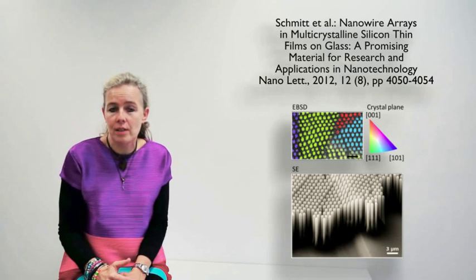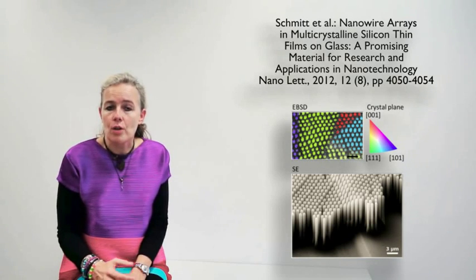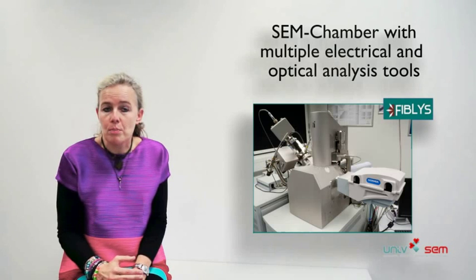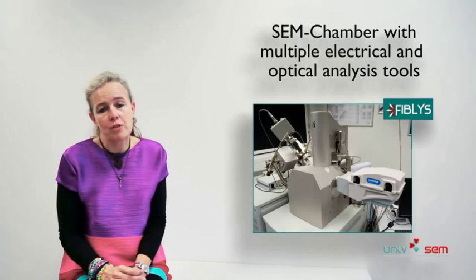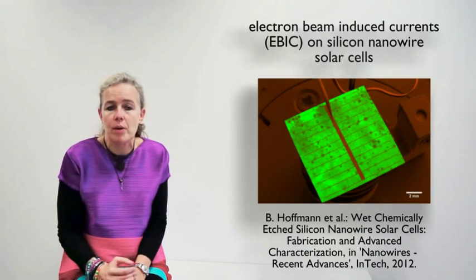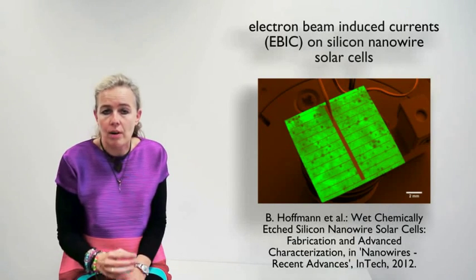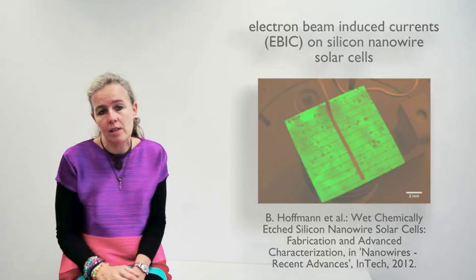So that's why we improved on that and this required a lot of electrical and optical characterization in order to improve and optimize the material. And for that we have big labs working on electron microscopies as well as microscopies with add-ons like electron backscatter diffraction, where we can learn about defect population with electron beam induced current, where we can learn about proper doping of the material and where the current resides, where junctions reside, all building blocks in solar cells. So we had to also improve our techniques to characterize those materials at the micro and nano scale. This has already required a lot of research since 2008 and the progress was remarkable.